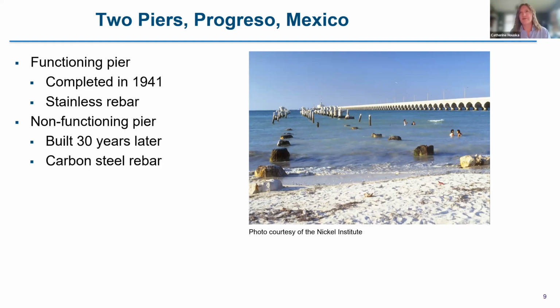It's just fine. That non-functional pier was built 30 years after the stainless steel reinforced pier, and it was non-functional within that period, within 30 years. And that was carbon steel black bar. Now, yes, you could potentially coat it, but there are a lot of states and provinces in North America that have banned coated rebar.